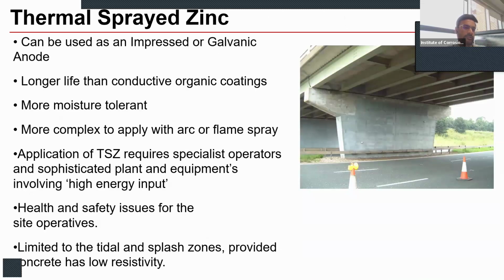Next type of anode we have is thermally sprayed. They can be used as either impressed current or galvanic kind of system, compared to the conductive coating systems they have longer life, sustaining up to 10 to 25 years of service life, with more moisture tolerance and more complex profile. However, they require specialist operators, plants and equipment, which involves high energy and has had some health and safety issues in the past for site operatives, although they are limited to tidal and splash zones, provided concrete has low resistivity. For this kind of system, the primary anode connector typically used is either stainless steel or titanium wires embedded in the process system.